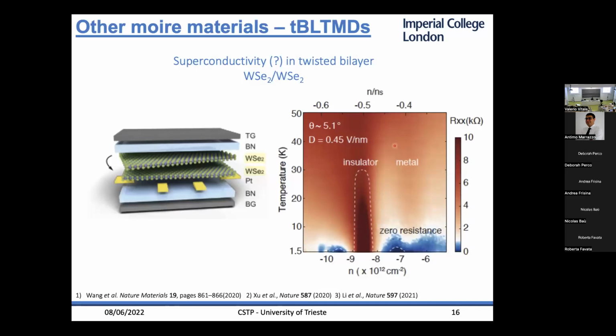But there are also, as I said, other materials that we can play with. So bilayer graphene is not the only one that shows these correlated states. Similar physics also happens in a completely different material, tungsten selenide, which is not a semimetal, but a semiconductor with a band gap of around 1-2 eV. But here as well, the phase diagram has these zero resistance states that haven't been fully identified as superconducting states. And in between these zero resistance states, there's an insulator state.